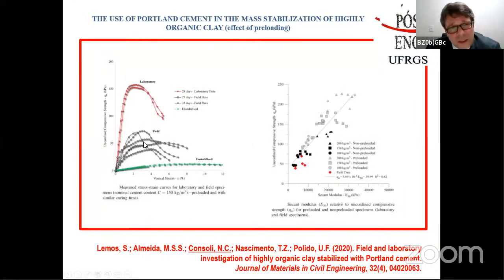Here we got specimens from the field and from the lab. And of course, as I said before, the artisanal mix in the field depends on the operator and so it's not so perfect. And so in the field, we got a strength that is about half of the strengths that we have in the lab. So these are the difficulties that we have in the field to mix. But even though, it increases the strength a lot compared to the unstabilized material that is right below here.